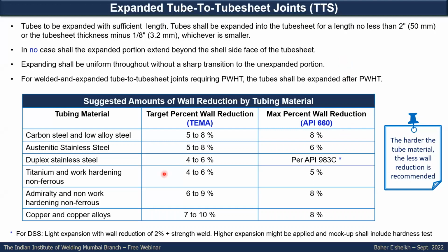We will see that for ductile material like carbon steel or low alloy steel, you can apply up to 8%. Between the two common standards in the industry, TEMA, Tubular Exchanger Manufacturers Association, or API 660, the standard for shell and tube heat exchangers, there is some minor variation in the recommendation, but almost they have the same approach on the recommended percent of expansion. What we can see here is that for the duplex stainless steel and the austenitic stainless steel, you have a little bit less recommended target wall reduction or expansion, while for the copper alloys and also for the carbon steel or low alloy steel, you can apply a higher degree of expansion without any issue.